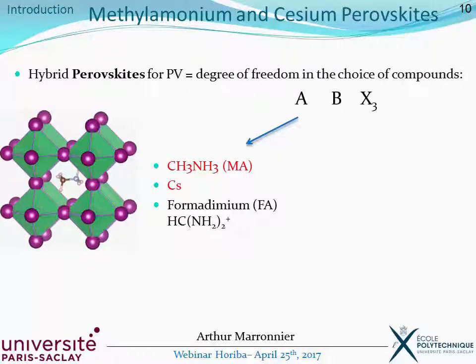Then, this methylammonium molecule that you can see on the picture here at the center is surrounded by inorganic octahedra made of mainly lead for the B part and halide ions for the last part X3. Here we'll be talking about iodide perovskite, but you can also have bromide or chloride. So you can see that you have quite a large number of degrees of freedom in the choice of compounds for these hybrid perovskites for photovoltaics.